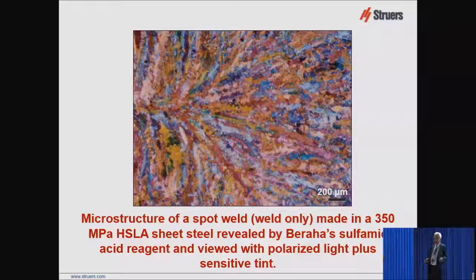The fourth one has an addition of ammonium bifluoride, and allows you to color etch steels up to about 18% or so chromium, like 440C martensitic stainless steel, things like that. And I've used it extensively over the years. Now, all you're seeing here is the spot weld only. You're not seeing any base metal nor heat affected zone. But the center of the weld is over here, and you can see the flow pattern of the weld as it's solidifying.